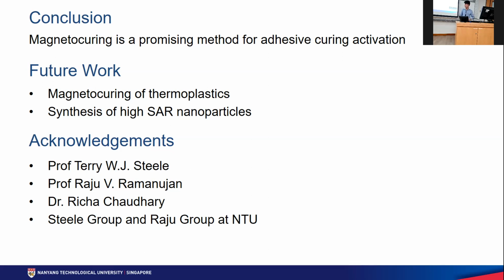Mechanical performance wise, because I'm adding these nanoparticles at a very low rate, 1 weight%, the mechanical testing is actually between a magneto cured state and a neat adhesive state. So I think it's more about how the neat and magneto pieces are activated for the process of polymerization, the different types of initiation that result in the different mechanical properties, rather than the addition of particles.